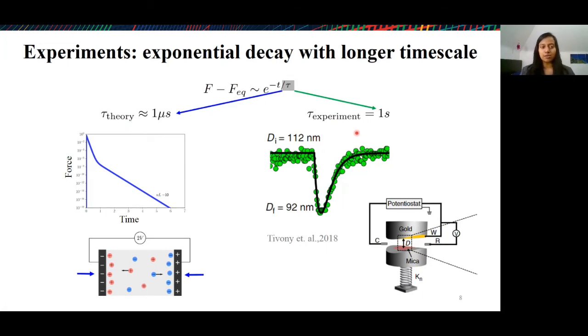And so I just want to take a minute to put forth some of the reasons for this. Again, we consider a model electrochemical cell, and the main difference between our system and the experimental system is that in our cell, we consider one-dimensional transport just between these two electrodes, and the ion transport is only perpendicular to the electrodes. In the experimental system, it's really not just ion transport between these two surfaces, but rather ions move from this bulk reservoir surrounding the two surfaces into the gap between the two surfaces. So there is also some component of tangential transport parallel to the electrodes, which is in fact what causes this much larger timescale. So there's definitely room for adding multidimensional transport to our theory.